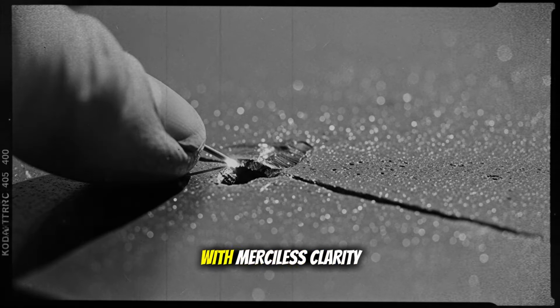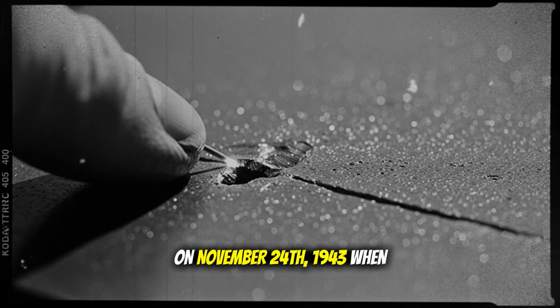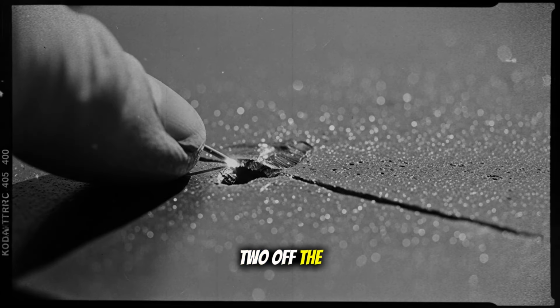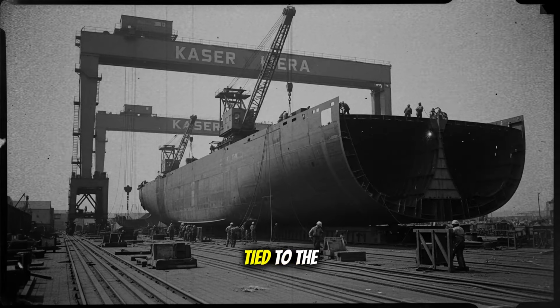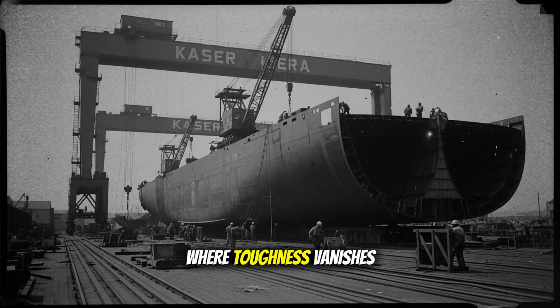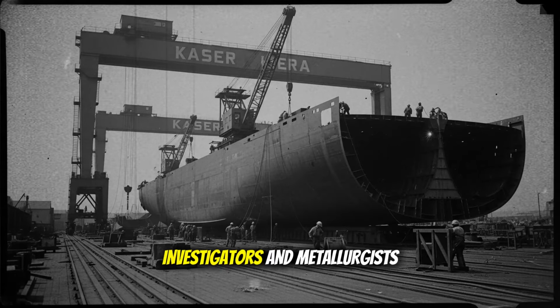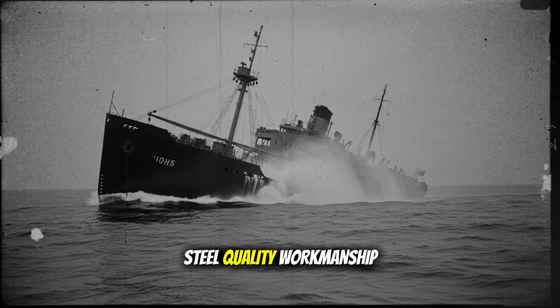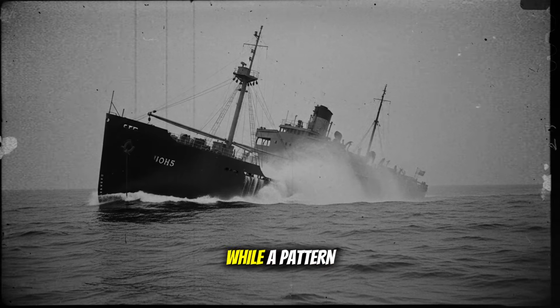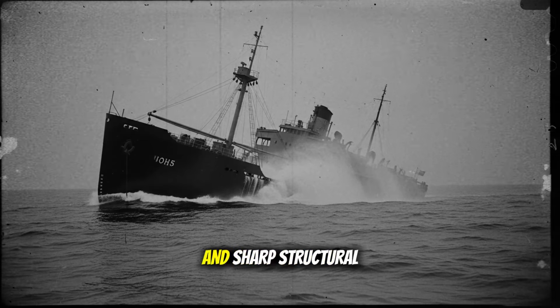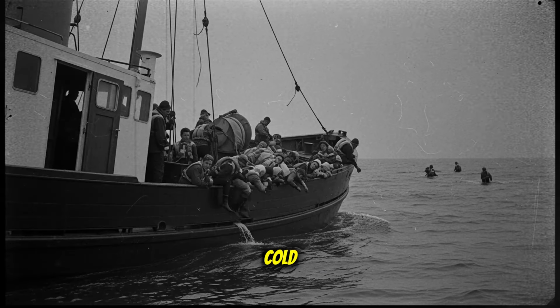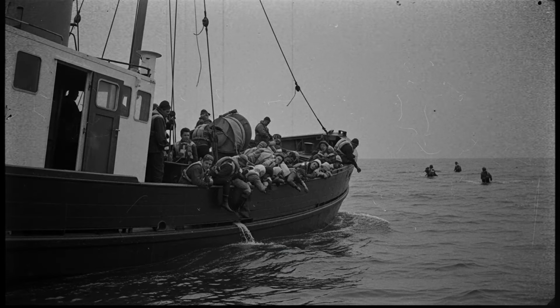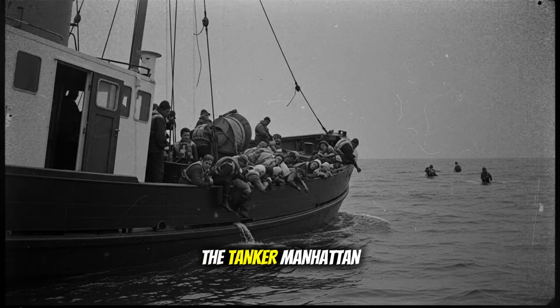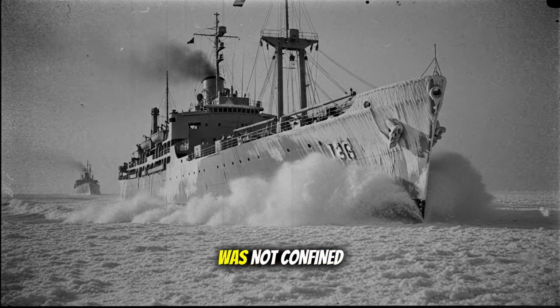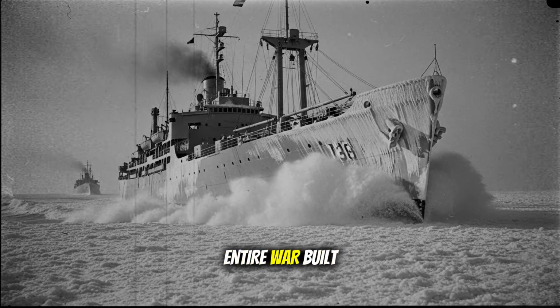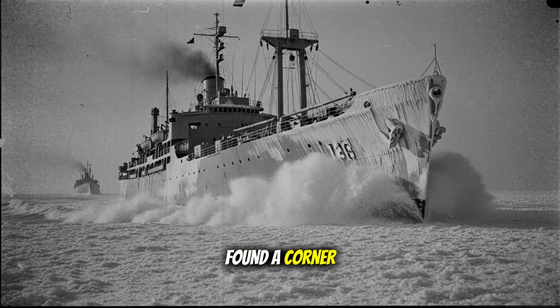Out at sea, proof would come with merciless clarity on November 24, 1943, when the Liberty ship John P. Gaines broke in two off the Aleutians and sank with 10 lives lost, a catastrophe later tied to the embrittlement of welded steel in freezing waters where toughness vanishes and cracks run unchecked. Investigators and metallurgists began naming factors: steel quality, workmanship, temperature, stress concentration, while a pattern emerged: ships with long, continuous welds and sharp structural details were prone to sudden brittle failure when cold stripped the metal of its ability to absorb strain. Even near New York in March 1943, the tanker Manhattan reportedly broke in two, underlining that the menace was not confined to a single yard or coast but haunted the entire war-built merchant fleet when the thermometer fell and the stress found a corner to concentrate.